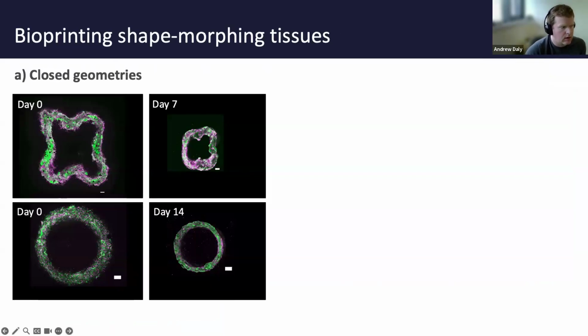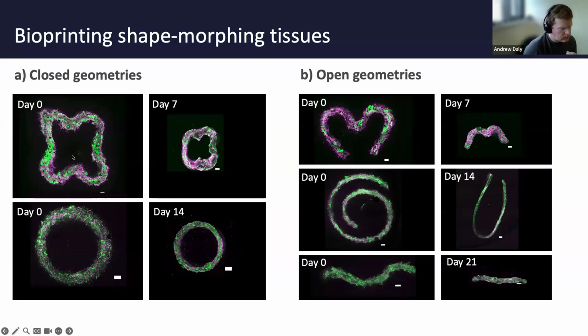And here you're looking at cells fluorescently labeled in magenta, and we've also labeled the collagen with this green stain. It was interesting to us that if you print something simple like a tube, it will shrink over time, so over 14 days of culture. That's caused by cells pulling on the matrix and creating a smaller construct. If you change the geometry, you get a different shape morphing process.